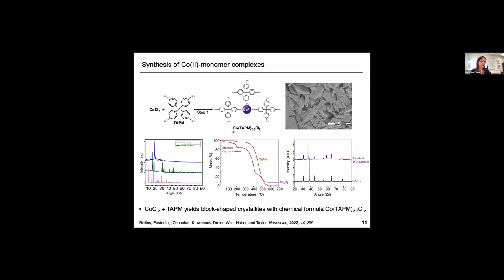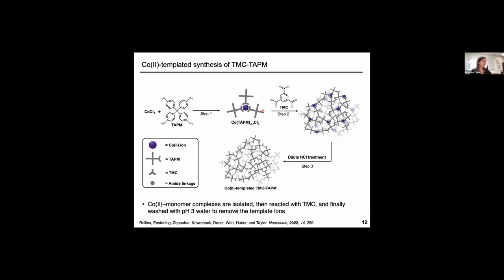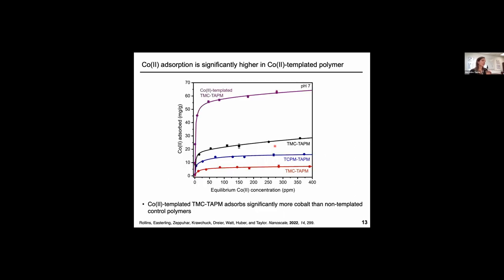So then with these cobalt monomer complexes in hand, we continued down the synthetic route. This is a representation of the cobalt monomer complex. We combined it with this trimesoyl chloride molecule to get a cross-linked insoluble network. We use dilute acid to wash away the cobalt ions and leave behind an activated polymer. So then this polymer is what we wanted to test for its cobalt adsorption capacity. And this is the banner result of the project. Our cobalt templated polymer takes up a significantly greater amount of cobalt ions from aqueous solution compared to any of those non-templated polymers that I described earlier.